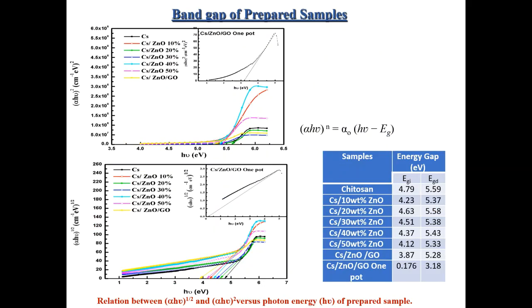Values of both direct and indirect band gap energy were calculated by extending the straight line from the linear part of the curve to the h nu axis. As seen, with increasing the filler, values of direct and indirect band gap energy decreased compared to pure chitosan, and it has a lower value for chitosan doped with zinc oxide and graphene oxide. Previous results showed that chitosan zinc oxide graphene oxide prepared by the one-pot hybrid method reduced the disorder and is the best preparation method for the use of chitosan zinc oxide graphene oxide as optoelectronic material.